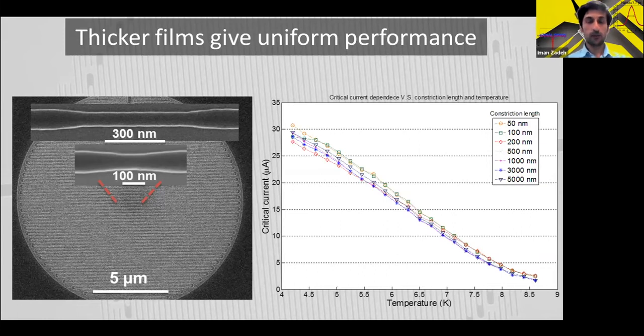And that solved one major problem with our material platforms, because usually some groups prefer to use amorphous superconductors. It's a little bit easier to optimize, and a little bit easier to work with, because if you have a long detector and you have different crystalline regions of one phase or other phase, they might have different superconducting behavior, and that leads to reduced performance of the device.